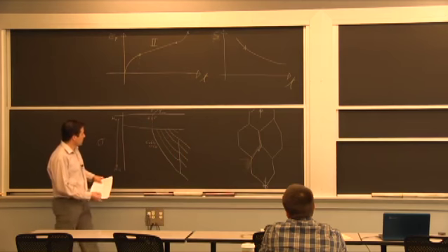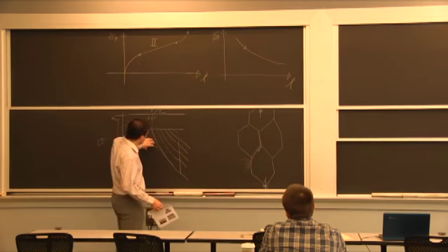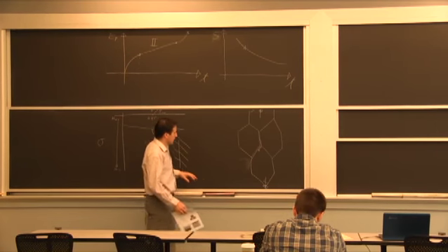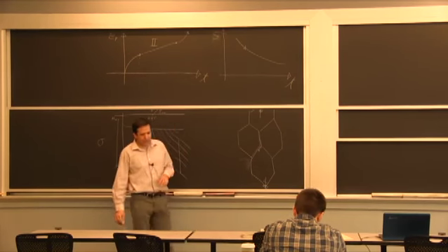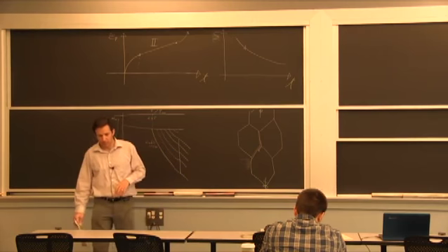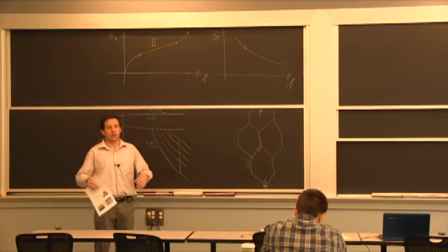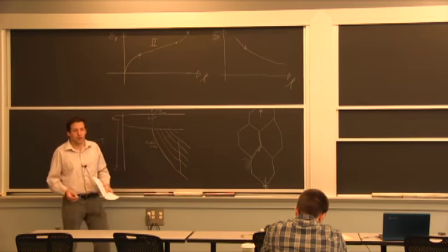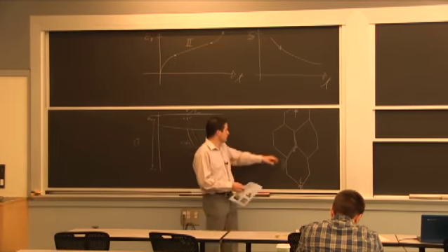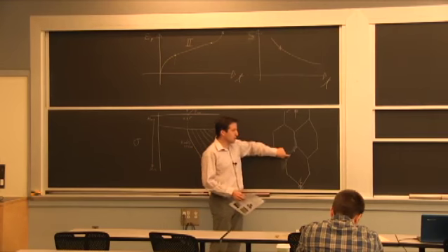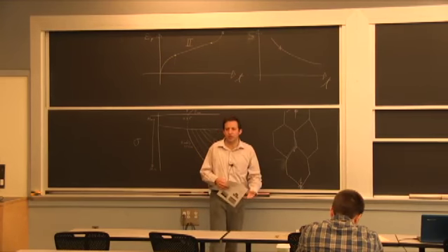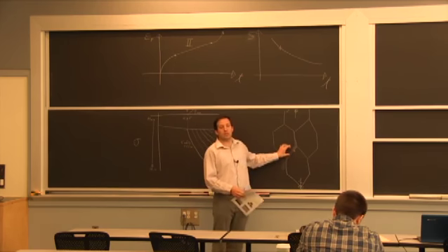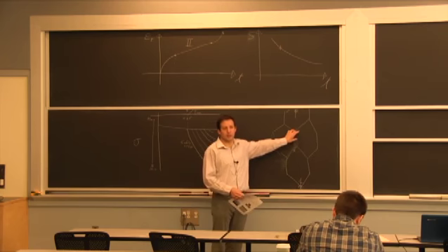It happens in the low temperature side, and therefore you don't have a whole lot of vibration to make that diffusion. This is a diffusion process. You're asking the atoms to relocate from this position to this position, and they'll do it naturally because there's a driving force. Over here, there's a little bit more spacing in that boundary than there is in the other one